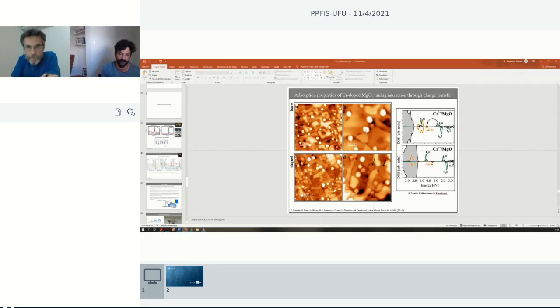No, but I understood. It's basically the size. The size can be such that it will have an extremely different electronic structure. It will act like a quantum dot in some cases, like you said, with Coulomb blockade, for example. I mean, they are different. This example here is nice. It's work with Pacchioni from Milano. What's happening is, of course, these particles are sitting somewhere, on top of the oxide. So if you look at the orbitals that are contributing, let's say, for the overall material, they are sitting somewhere in the band gap of this material. So they are not part of the material, but they are sitting at the Fermi energy, in an electron reservoir, that's the oxide.